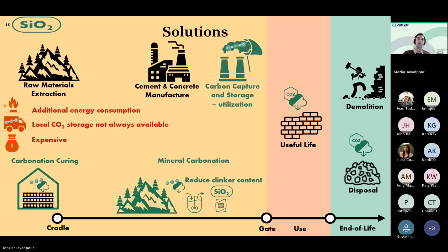The second pathway is mineral carbonation. Now, mineral carbonation, we take the CO2 and we react it with minerals rich in calcium or magnesium silicates to produce a supplementary cementitious material, which, if you've forgotten, those materials that we replace clinker with. And in this case, it's silica, amorphous silica, that can reduce the clinker content in concrete while also sequestering CO2 within that process, right? So now, instead of just taking that CO2 and then dumping it somewhere underground, we have uses for CO2 within the concrete life cycle in itself.